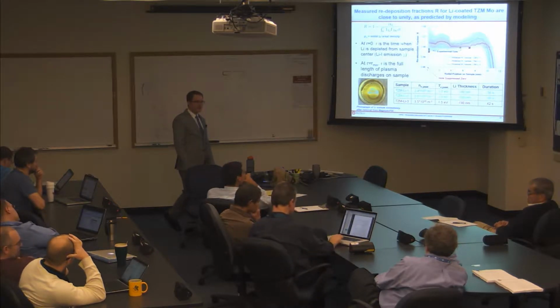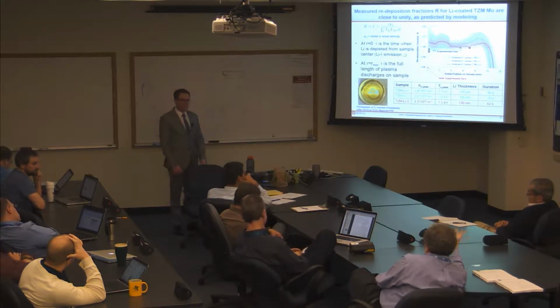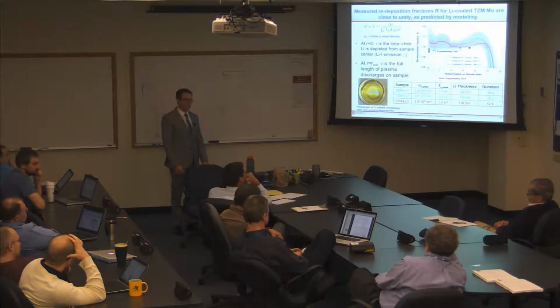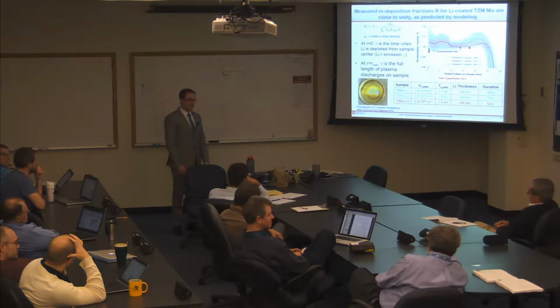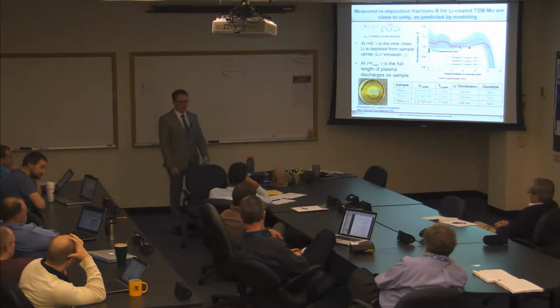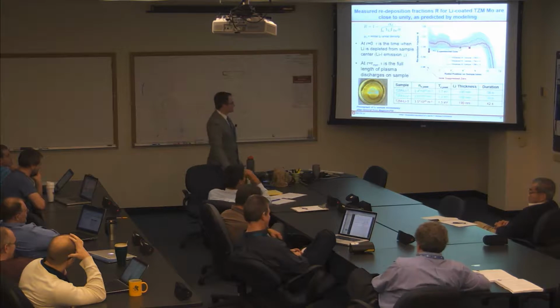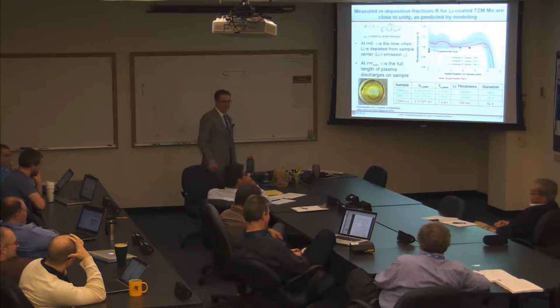Right, I mean, couldn't you use the model to just deplete the lithium and actually model that radius where it disappears? Did you try that? I did not try that. A real brute fact about that is it's 2 centimeters of minimum radius. You blew it all away, and then it showed up somewhere else. Yes. It's interesting to see if your model did that. Well, this data has not been published yet, so that's still a possibility. Well, if it had been published, you get a second publication.